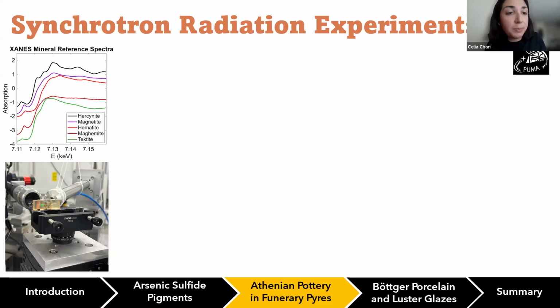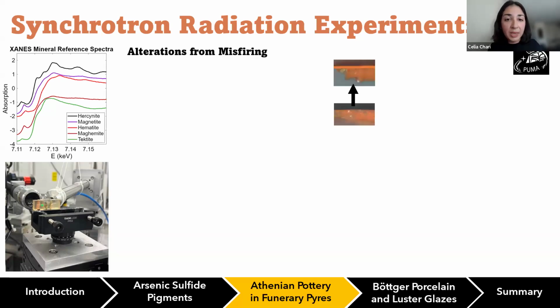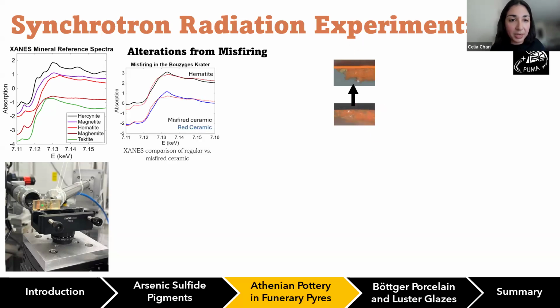We were fortunate enough to be able to get some mineral samples from Harvard's Mineralogical Museum, including hercynite, magnetite, hematite, maghemite, and also tektite. And we compared the XANES spectra of these iron oxides directly to our samples. So first, starting with alterations from misfiring, this is where we're seeing that the regular black gloss over the red ceramic is oxidizing into this red gloss over the red ceramic.